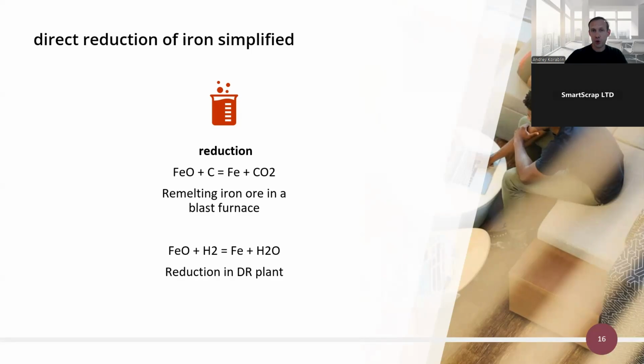When we add coke, a carbon-containing material, and iron ore, which is iron in oxide form, into the blast furnace, a chemical reaction occurs due to the heat. Oxygen interacts with carbon, and as a result, oxygen separates from the iron molecule, producing pig iron, or liquid iron with a high carbon content from 3 to 5%, and carbon dioxide.